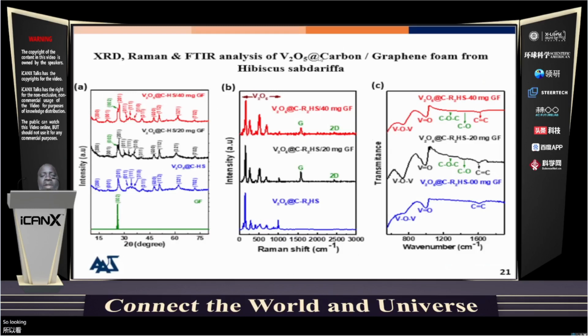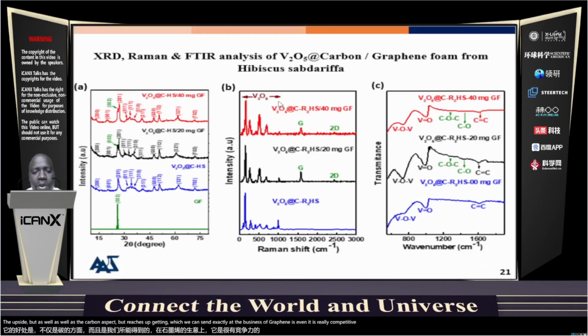Looking also at the Raman, it confirmed what we previously obtained on the X-ray diffraction, which is the oxide part, as well as the carbon aspect, which is appearing. This confirms that the graphene is really embedded into the vanadium pentoxide carbon material, which is further confirmed by the FTIR, Fourier transform infrared spectroscopy.